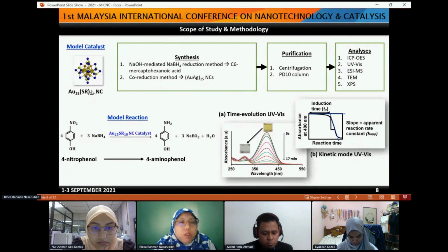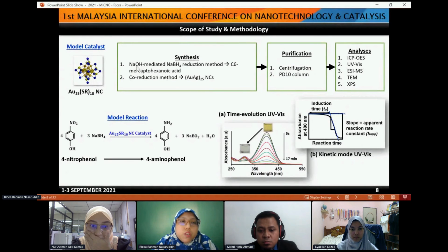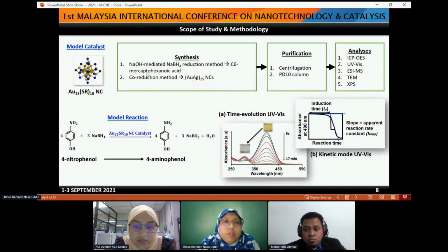So we are focusing on gold 25. It means that we are producing this 25-metal nanocluster. It means that in one particular nanocluster, you will just have 25 metal atoms. And the method that we use is the sodium hydroxide mediated sodium borohydride reduction method. And the ligand for this particular study is C6 mercaptohexanoic acid. And we use the co-reduction method for both silver and gold precursors.